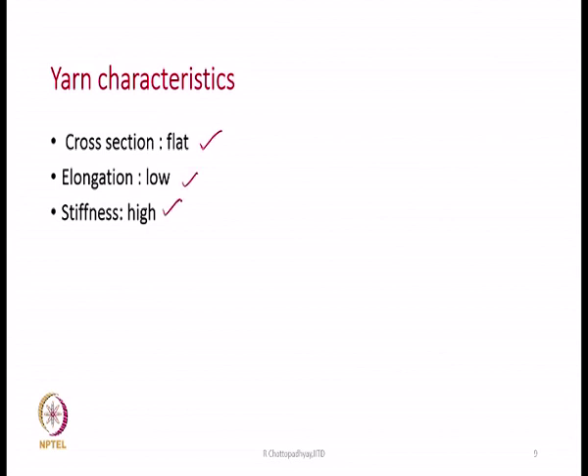Elongation will be low, stiffness will be high. Why? Because there is no twist in the fibers. Since twist is not there, the initial modulus is going to be quite high, and for the same reason, the elongation is also going to be quite low. So, all these yarns will show higher stiffness and low elongation, in comparison to the yarn made from the same fibers on other technologies, that is either on ring spinning or maybe on vortex spinning. Evenness is similar to ring yarn.